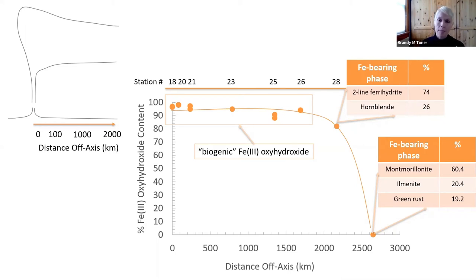So a couple of things. It was surprising to us. I would say that what we saw here in terms of the iron speciation at the ridge axis and within about 100 kilometers wasn't too surprising. We were anticipating that there would be some aging or ripening of those iron 3 bearing materials into more stable phases during transport, perhaps. That is not what we observed. It's always possible that some of that was going on and those were materials that filtered out, meaning settled out to the sediments. But this was surprising also, to see that the chemistry was so uniform over such a long distance of transport.